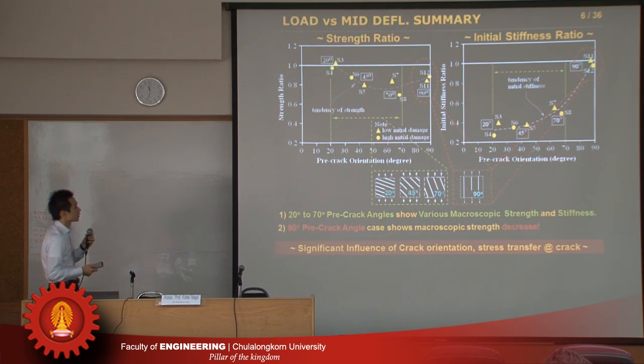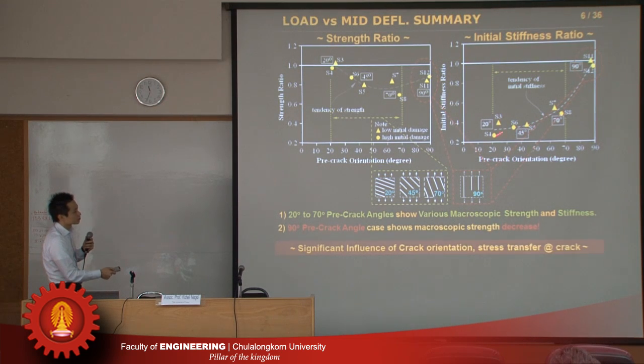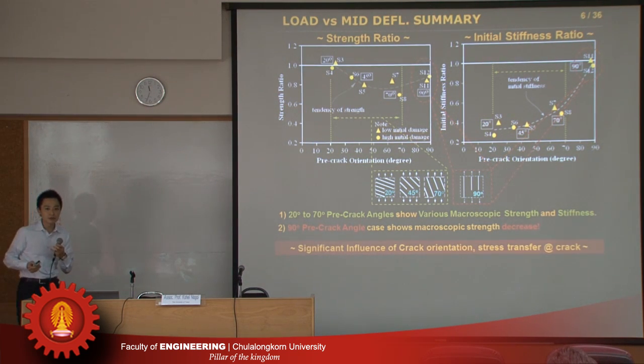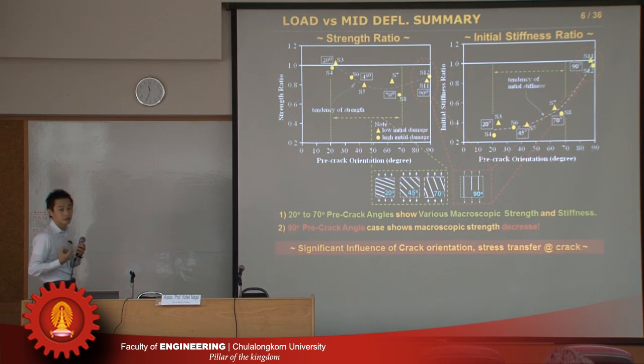So this slide summarizes the strength reduction ratio and initial stiffness reduction ratio against the pre-crack orientations. For 20 degrees, we do not have the strength reduction, but increasing the angle, yes, we have a reduction, and for 90, a little bit recovered. And initial stiffness, yes, 20 degrees decreases more and recovers like this. So why this kind of phenomenon happens can be explained by a detailed investigation of the phenomena.